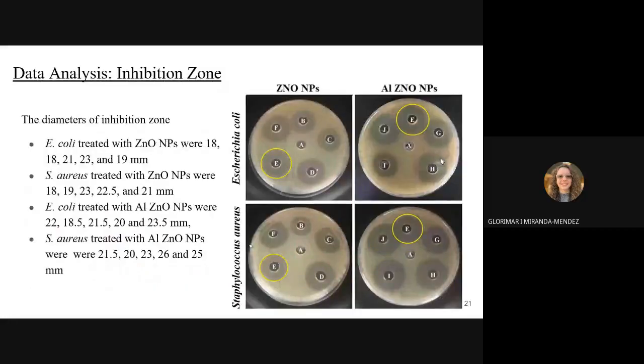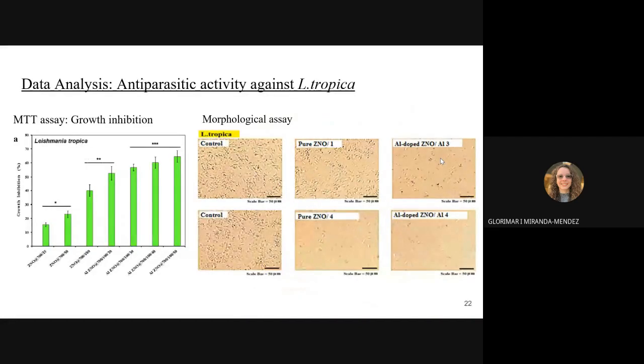Okay. So they also determined the inhibition rate of the antibacterial to determine the same type of trend as the previous analysis. They also did the antiparasitic activity. They basically took a culture and determined the growth inhibition to determine also an escalating trend, with the doped nanoparticles with the max inhibition rate. And they also, with the morphological assay, they determined